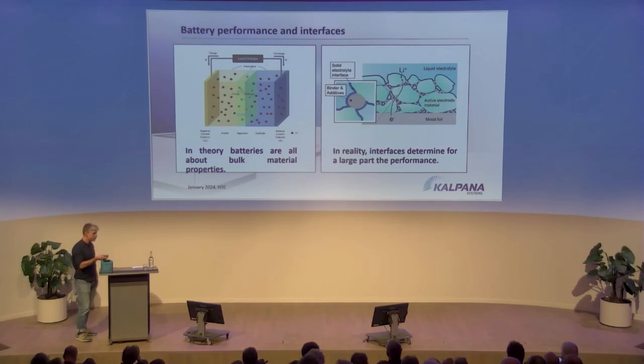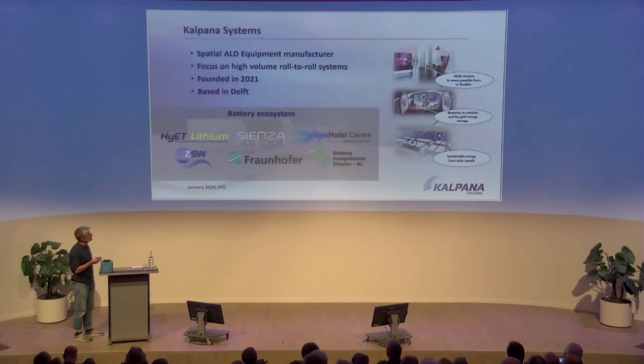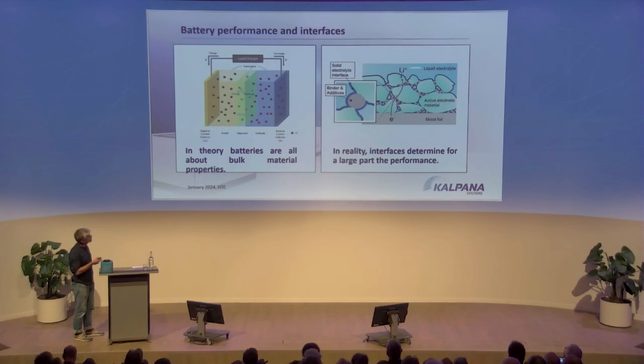But when you really look into detail at what a battery looks like, there's actually a lot of surface involved. So the electrodes are usually porous. The electrolyte is going all the way into the electrode. And this interface determines for a large part the performance of the battery. So when you start charging and discharging a battery, usually the organic electrolyte will react chemically with the electrodes, and you will form a solid electrolyte interface. And this interface can of course have many properties. It can be insulating, it can be ion conductive. So the properties of this surface determine the actual performance of the battery.